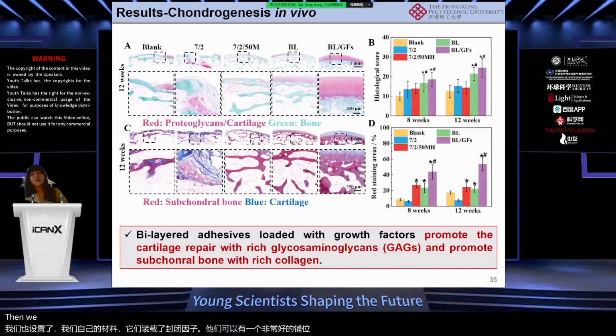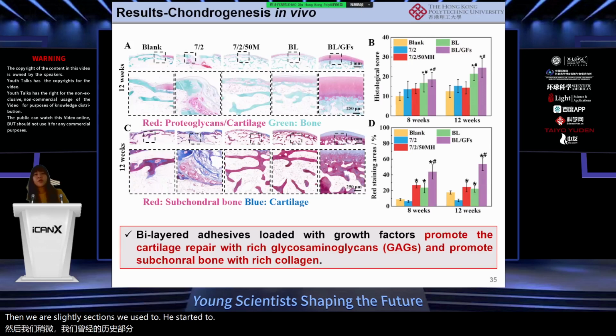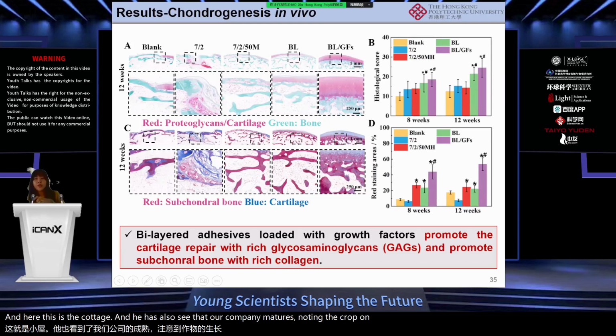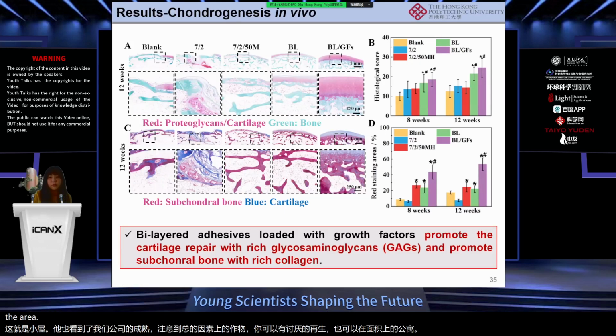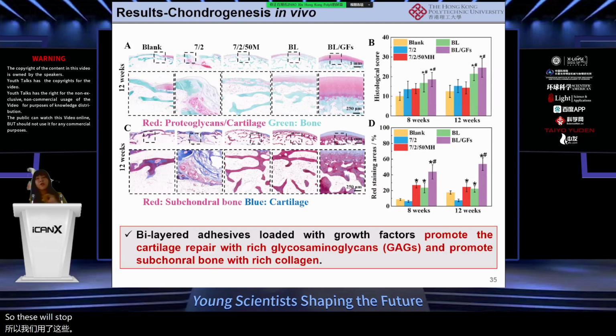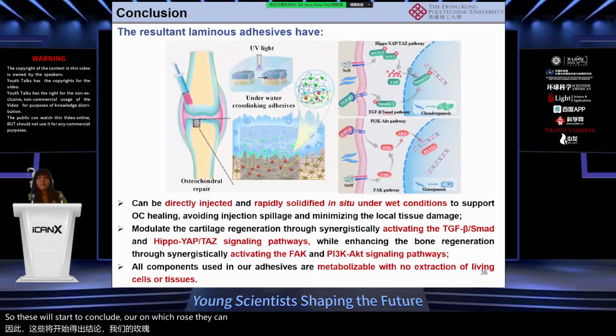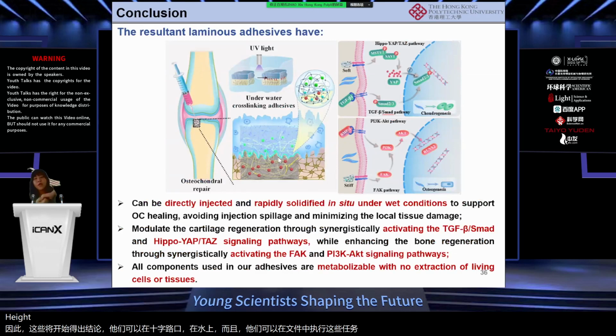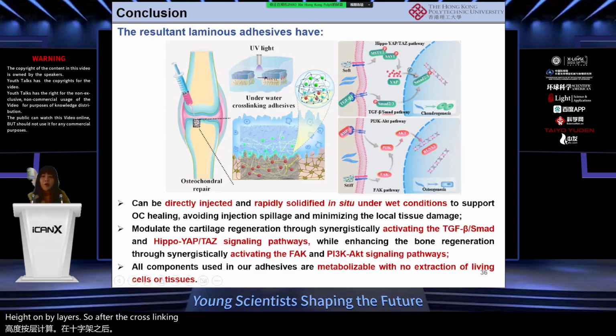And then we slice these sections. We use the histology to examine the different sections. And we can see that these colors, so here, this is the cartilage, and here, this is the cartilage. And we can also see that our composite materials loading the growth factors can have nicely regenerated osteochondral area. So to conclude, our materials can be cross-linked underwater, and also they can form these tight bilayers after the cross-linking, and also they can help regenerate both the cartilage and also the bone.